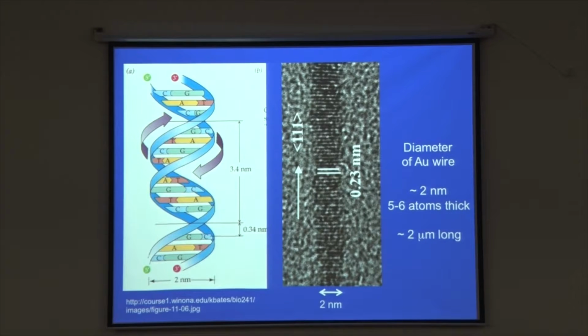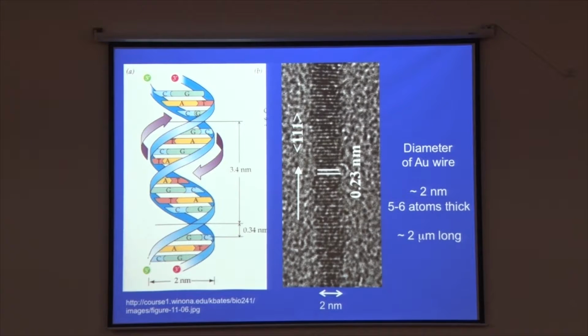First of all, what do you mean by ultra thin? I think all of you recognize this structure here. If you look at the dimensions here, it is of the order of 2 nanometers. The gold nanowires that we have been able to make in the lab without any template are of similar dimensions. These are 2 nanometers or slightly below 2 nanometers in diameter. If you think about it, these are about 5 to 6 atoms thick. So these are really thin wires that we have been able to make using a fairly simple method. And of course, these are fairly long, 2 microns long, which means that the aspect ratio is more than 1000. And this is a very simple method where we can make it.